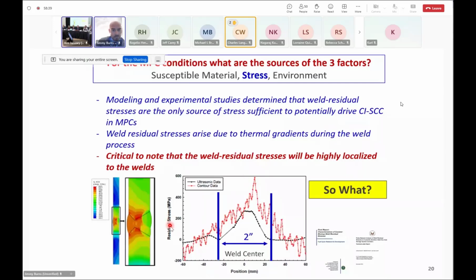And then on the y-axis is the residual stress. And so what this shows is from the center of the weld going out, your residual stress essentially goes to 0 about 1 inch away from the weld center. And so 1 inch on either side, or 2 inches surrounding the weld center, is the only place where you have a residual stress field. Okay, and this is data, and the details of how it was generated can be found in the reports. But so what?